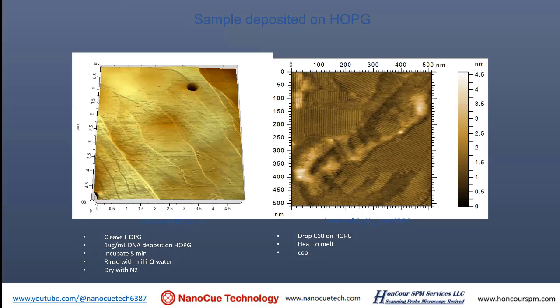If your AFM tip is not atomically sharp, it has a certain size. So you measure the width, or how sharp it is. The step can tell you how sharp the tip is. Okay, and the image on the right is a sample that people often run to test the ultimate resolution of your AFM. This is a tapping mode image of C60, C60H122, on HOPG. They will form a self-assembled organized layer. After the layer forms, you can image the surface and see these nicely aligned atomic layers side by side. It's a good way to test the sharpness of your tip and your skill.